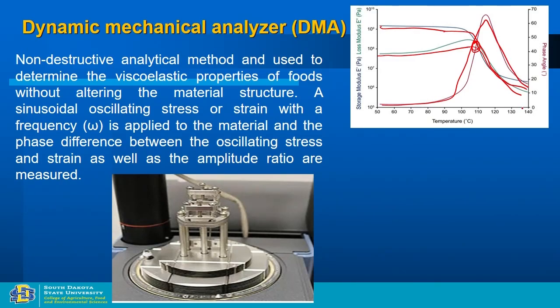So, if you look at the phase angle, it can go up to 68 degrees. So, what it means is it is closer to more of a liquid than the elastic nature, because at higher temperature it gets softened, so it became more liquid, but initially it is less than 10. So, it is a more elastic material at low temperature. At a higher temperature it shows the viscous nature.